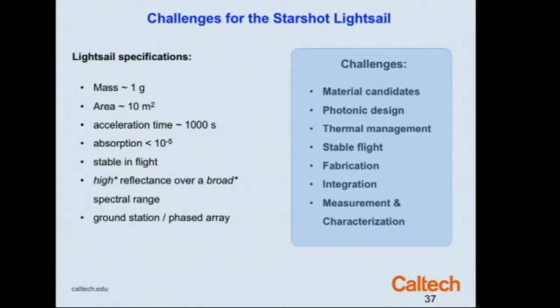So what are the issues for the materials challenges? We have a mass of a gram, area, call it 10 square meters, acceleration time of 1,000 seconds. We need to have very, very low absorption coefficient, otherwise the material will burn up. We have to have an absorption coefficient of 10 to the minus 5. We'll explain why that is important.